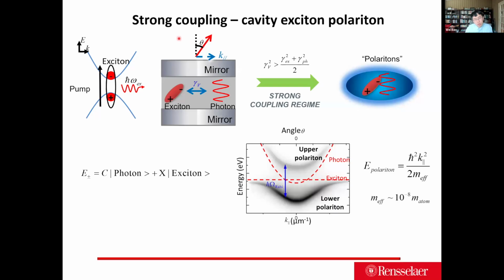The reason behind it is that if you try to see the photon with a cavity over different angles, the effective cavity length is going to be different. For example, if you look at this cavity at normal incidence, you see an effective length here, and if you come in with an angle, the effective length of the cavity becomes this. So essentially, the parabolic line shape represents the effective length change in the cavity. But once you form a strong coupling regime, the original E-K diagram will be renormalized into hybridized states. Essentially, we form an upper polariton and a lower polariton. These polariton states come from the hybridization of two bosons, one an exciton and one a photon, so they still maintain the boson state.